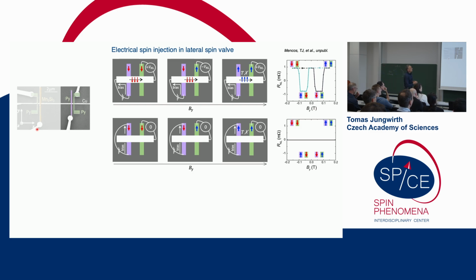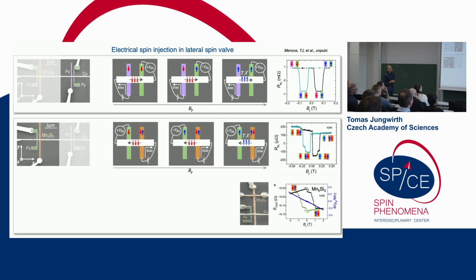So now let's take a look at what happens if instead of the ferromagnetic permalloy, I use manganese-5 silicide-3 (Mn5Si3). Again, this is now my injection electrode. Now the picture is just a mirror image because this is how they made their device. The reference and the manganese-5 silicide-3 (Mn5Si3) spin valves are actually mirror images. So now here I am biasing my injection electrode and the channel, hoping to inject spin polarized electrons into the channel, and then they will diffuse towards the detection electrode where I will detect them.